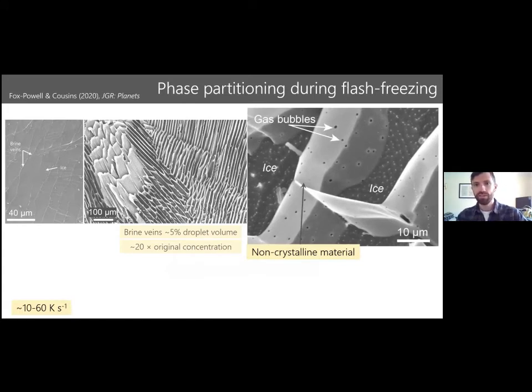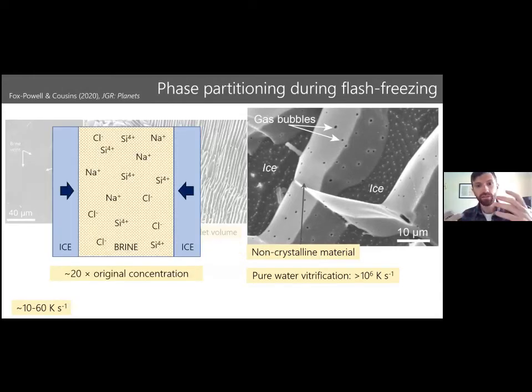Looking even closer at it though, we see that it's non-crystalline. It's a smooth, glass-like material that has these voids distributed evenly throughout, which are very evocative of gas bubbles. So this is strongly indicating that this material has vitrified. It has gone through a glass transition rather than crystallizing. This is unexpected because to get pure water or dilute fluids, like this brine actually, to vitrify in bulk, you need cooling rates that are way faster than anything we achieved in our experiments. The thing is though, as ice has formed and that brine vein network has been established, we've concentrated that fluid down, and the availability and high levels of solutes like this allow vitrification to occur at much, much slower cooling rates. So basically the conditions within those brine veins become very favorable for vitrification as they get concentrated.